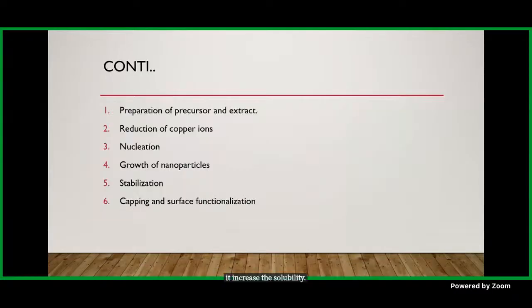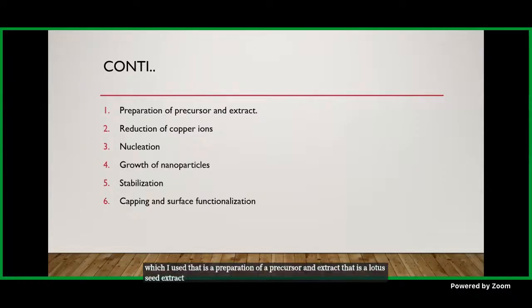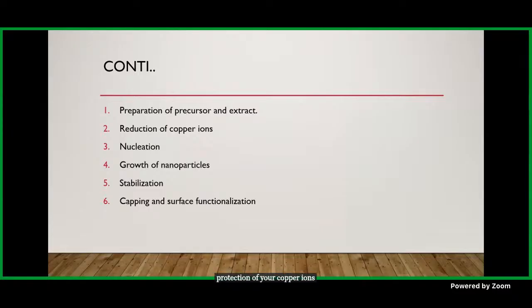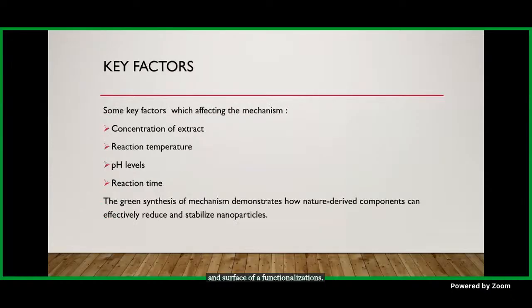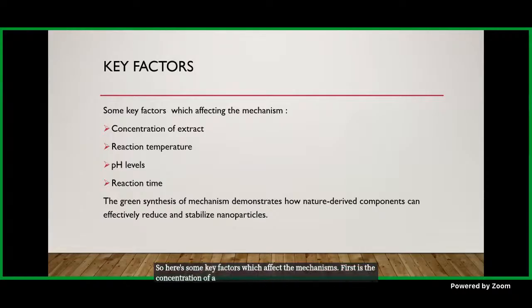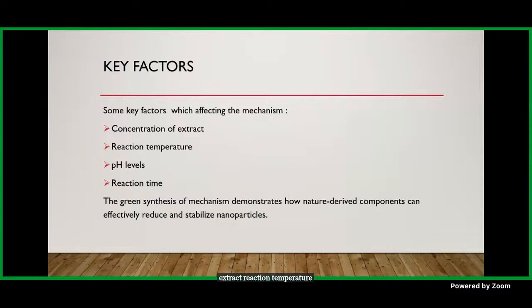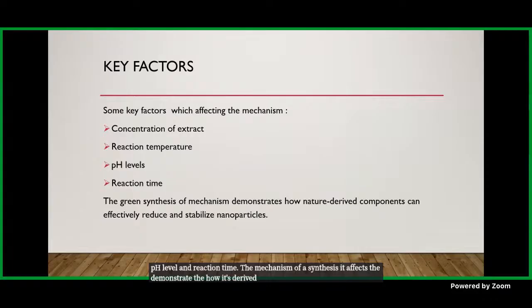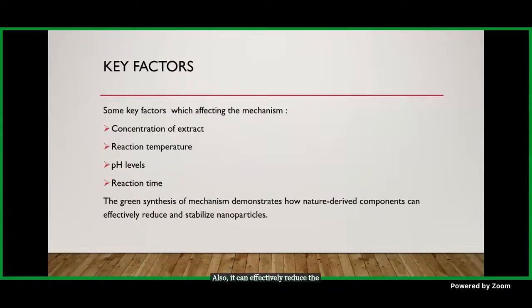Saponins facilitate nanoparticle dispersion and increase solubility. In the mechanism of synthesis, here are the steps which I used: preparation of the precursor and lotus seed extract, reduction of copper ions, nucleation, growth of the nanoparticle, stabilization, capping, and surface functionalization. Here are some key factors which affect the mechanism: concentration of the extract, reaction temperature, pH level, and reaction time. The mechanism of synthesis demonstrates how nature-derived components can effectively reduce and stabilize the nanoparticles.